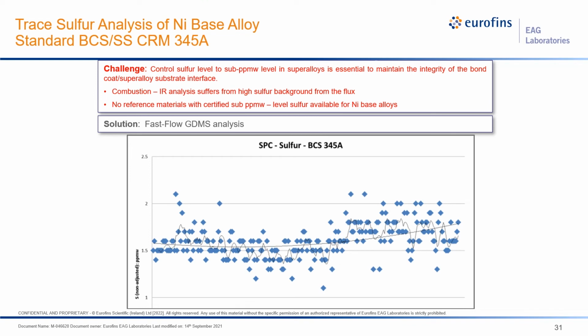One case study we want to present is a trace sulfur analysis for nickel-based alloys, because controlling the sulfur level to sub-ppm level in superalloys is essential to achieve the necessary performance target. Combustion IR analysis of sulfur suffers from high sulfur background from the flux. And there is no reference material with certified sub-ppm level sulfur available for nickel-based alloy. We managed to have one standard, 345A. It has around ppm level sulfur, and here shows you the SPC chart over a very long time period of how we monitored. This chart demonstrates that in our facility GDMS can be reliably used to monitor the sulfur level at sub-ppm levels also.